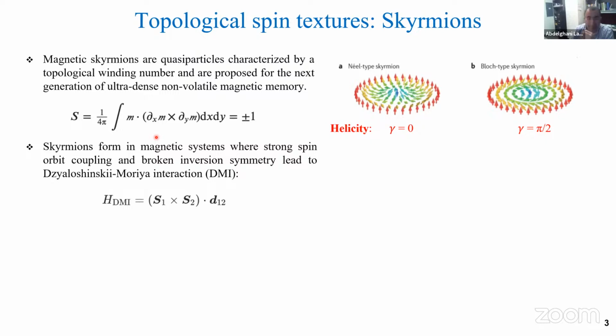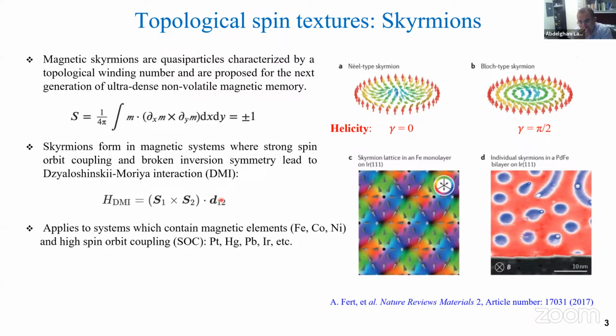Usually, skyrmions form in magnetic systems when you have broken inversion symmetry. So you have, due to spin orbit interaction, this DMI. In principle DMI is kind of an exchange coupling multiplied by this DMI constant. And usually you can observe this kind of skyrmions in systems where you have magnetic elements, for example, iron, cobalt, nickel, and high spin orbit coupling elements, I mean, platinum, iridium, etc.